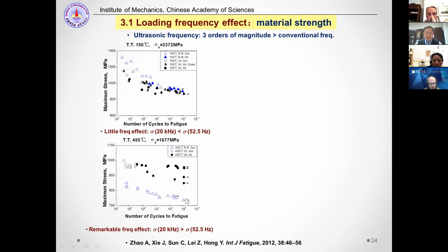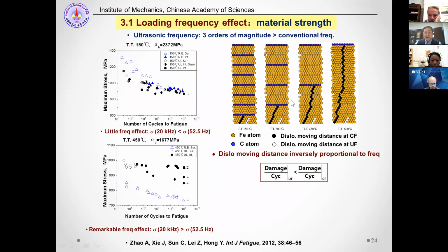But for the low strength state of the material, the frequency effect is very large, and the result is that the fatigue strength at ultrasonic frequency, that's very high frequency, is larger than at conventional frequency. And this is explained by these descriptions. Because for the high strength states, the microstructure is a kind of refined microstructure and contains a large amount of barriers, and they can restrict the dislocation movement. But for the low strength state material, the barrier is less, and there's limited restriction for the dislocation movement.